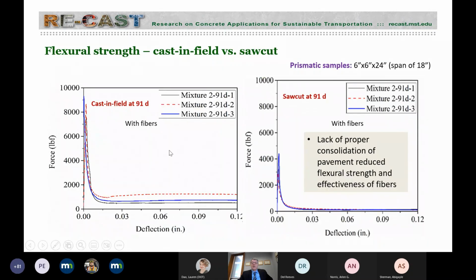So you can look more at the results of 91 days. So field cast versus saw-cut samples. We think as a main conclusion that the lack of proper consolidation of the pavement reduces the flexural strengths and the effectiveness of the fibers. From the initial testing, we saw-cut the samples because of the very, very dry consistency of the concrete, despite the fact that it's subjected to intensive consolidation. We felt that there was not enough bonding between the cement paste and the fibers to really activate and take advantage fully of those embedded fibers.